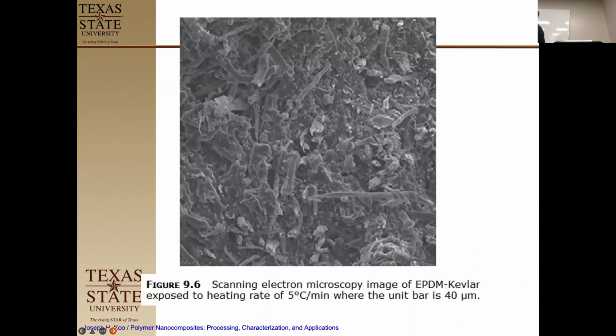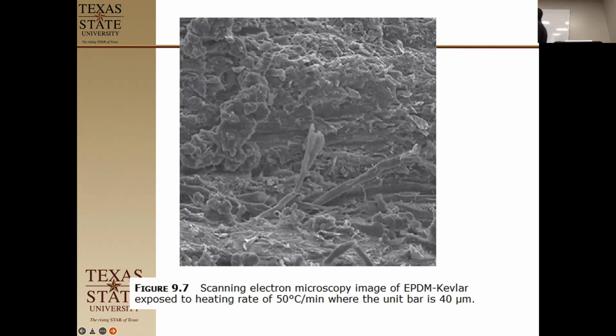And so they took a picture of it here. And this is at the 5 degrees a minute. And they see that it started as a smooth surface, so some of it has ablated away. The Kevlar nanofibers have pyrolized. And so they're now in that state, and there's nice porosity in the system. So that was at 15 weight%, I think. And then when you do it at the faster heat rate, you see that there seems to be a thicker char layer. So it's faster heat flux. And that's going to be closer to what a rocket motor would do, right? Because it's giving us this char.